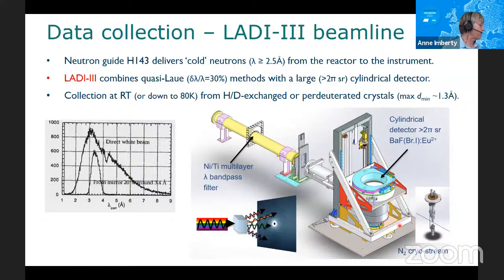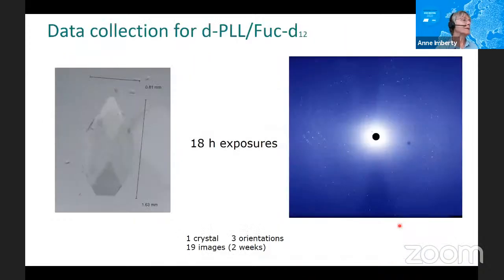From this, we moved to the LADI3 beamline. This is the Laue diffraction beamline at ILL, and I will not give you details because I'm not a specialist, just to say that this one has been the instrument that gave many of the neutron structures that are in PDB now. So from this, with our model system, our Photorhabdus lectin, from 18 hours of exposure, we could get Laue diffraction data of quality. And after 2 weeks of such measurements with 19 images, we could get the structure.